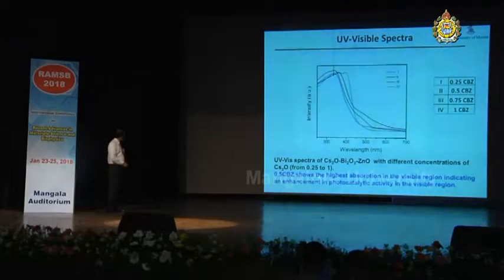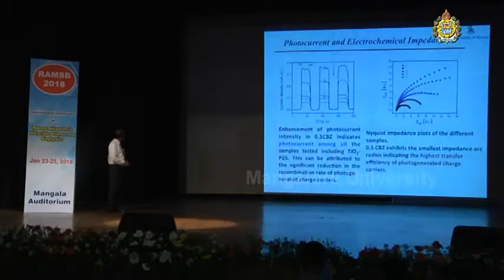that shows the highest absorption in the visible range, indicating the enhancement of photocatalytic activity in the visible range. As you can see here, it is extending to the visible range, and this you can further understand from the photocurrent and electrochemical impedance. As you can see, this is for the 0.5 CBZ, showing the highest photocurrent among all the samples tested, including the standard one, commercially available Degussa P25.